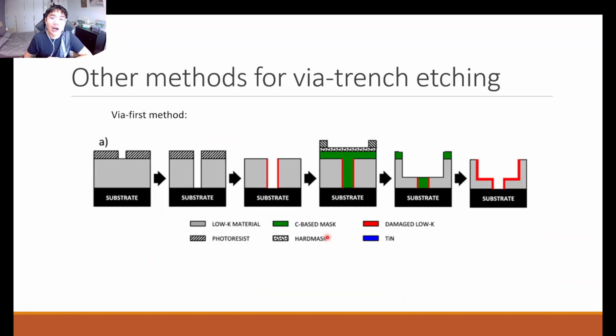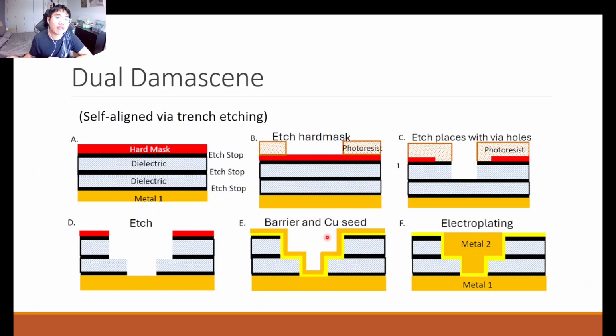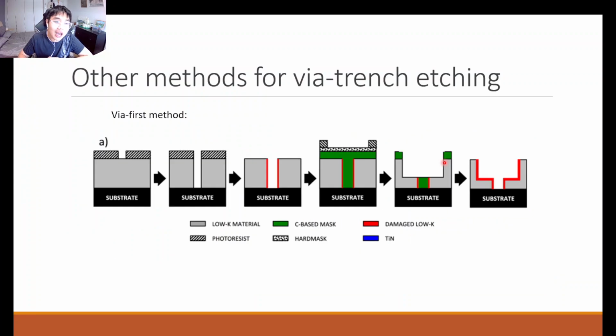Okay, however, in addition to this self-aligned trench method, there may be some issues with the self-alignment. So there's also another kind of via trench etching method that's widely done. The first is the via first method. So we etch down the via first, and then you fill up the via with something like a plug before you etch your trench. And then after you remove the via plug, you have your opened up via and trench that's ready for your plating of your copper or whatever interconnect method that you are going to use.